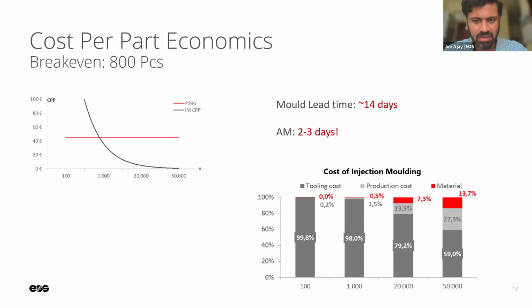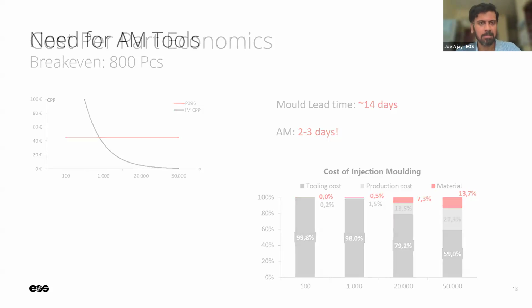But let's say if we go to bigger volume numbers, then we can see the economics come into play, that injection molding is far better, cheaper when we have large volumes. But where exactly is the break even? We found out that for this particular part it is roughly about 800 pieces. So this is geometry to geometry, and we can work on a few cases to understand where exactly we have the break even when we compare injection molding to direct parts with the SLS process.